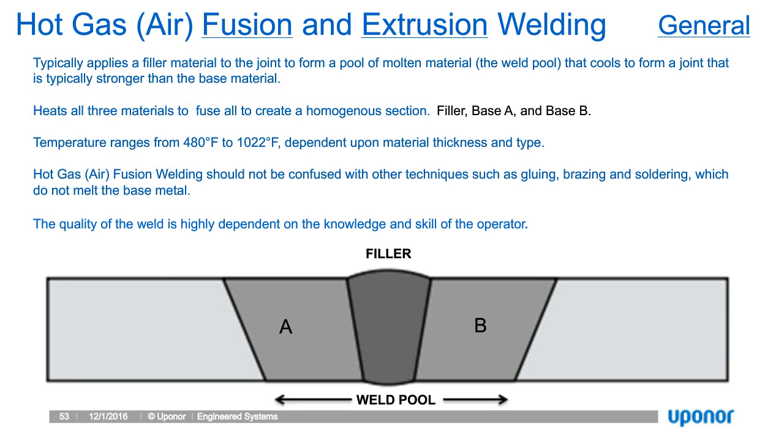And as we'll see in a second here when we talk about material testing, the weld seam is actually the strongest part of the section. The weld seam will have more material, will be a thicker section, and when we run it through tensile strength testing, our expectation is that the other material, either the A or B materials in the system, will fail and not the weld itself.